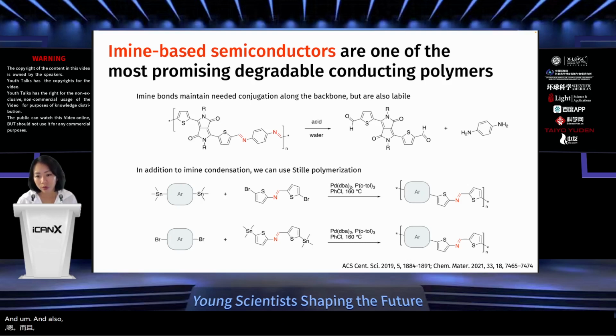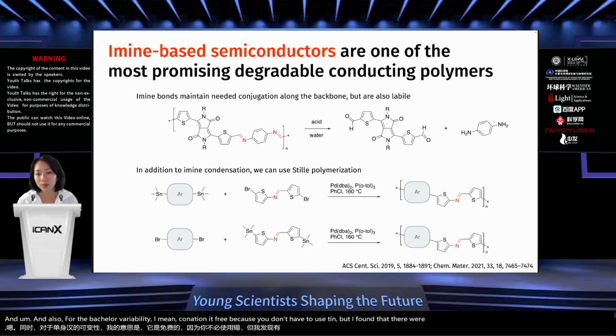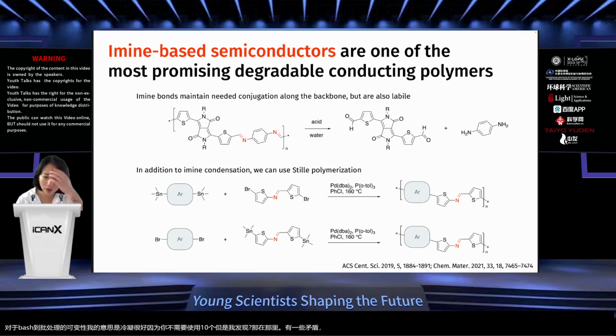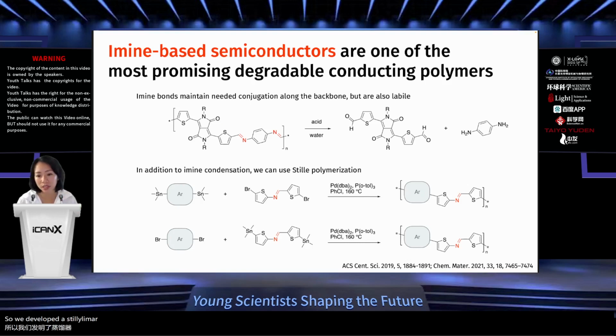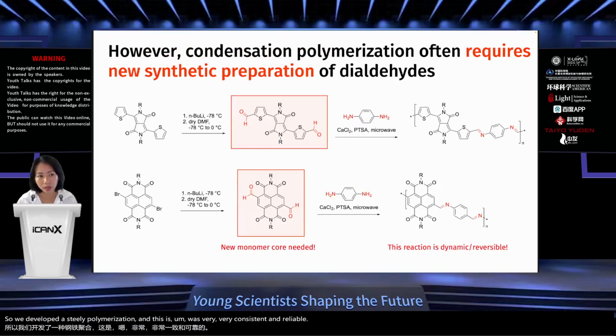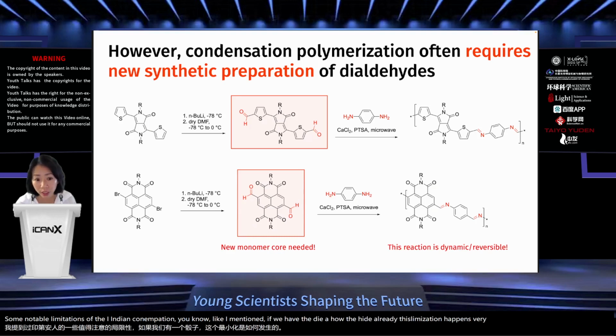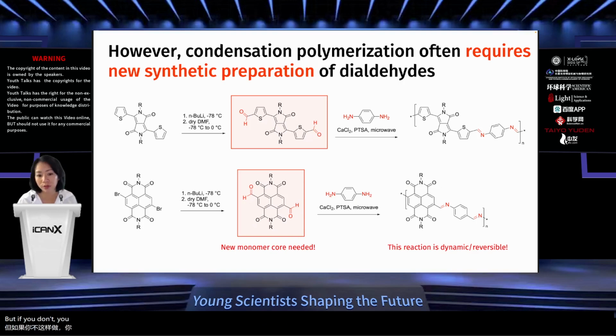And also for batch-to-batch variability, imine condensation is great because you don't have to use tin, but I found that there were some inconsistencies. So we developed a Stille polymerization, and this was very, very consistent and reliable. Some notable limitations of the imine condensation, like I mentioned: if we have the dialdehyde already, this polymerization happens very quickly. But if you don't, you have to devise new synthetic routes to produce this.